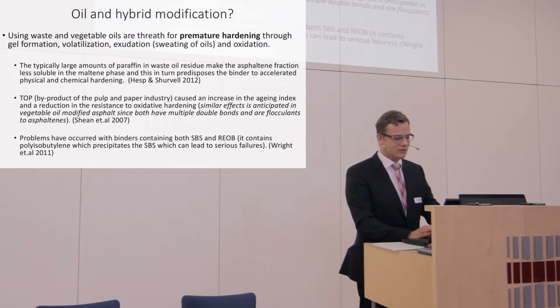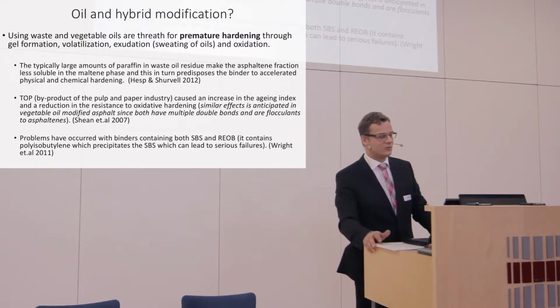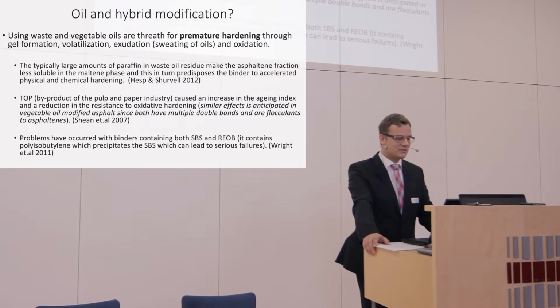Hesp and Sherwell in 2012 said that the typically large amounts of paraffin in waste oil residue makes the asphaltene fractions less soluble in the maltene phase, and this in turn predisposes the binder to accelerated physical and chemical hardening.